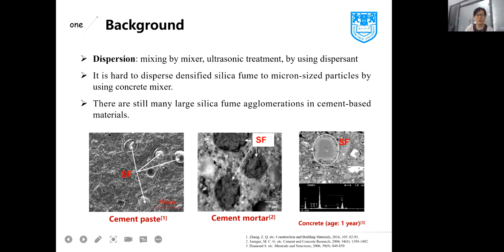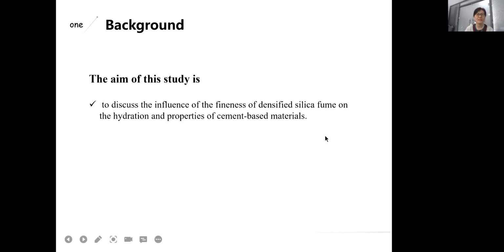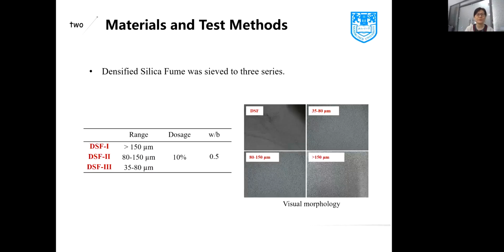From these 3 figures, you can see from cement paste, cement mortar, to concrete, even at 1 year of curing, there are still many large silica fume particles. So the aim of this study is to discuss the influence of the fineness of densified silica fume on the hydration and the properties of cement-based material. We just focus on the size of silica fume.